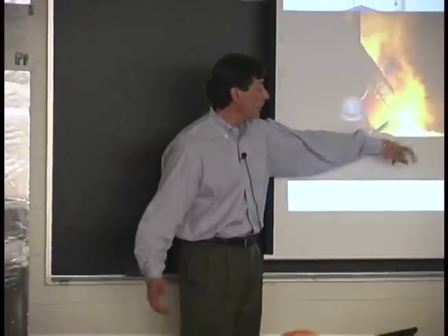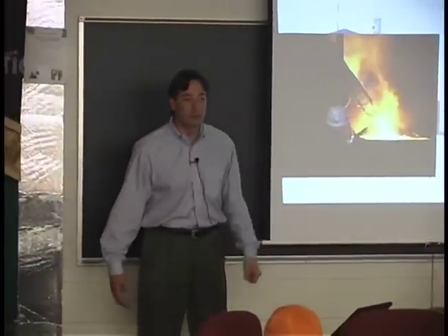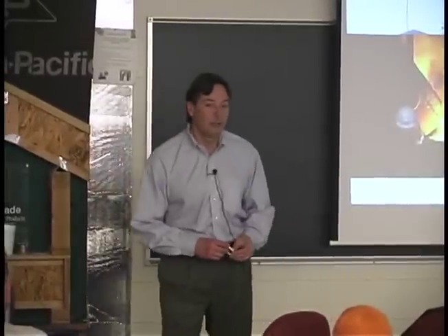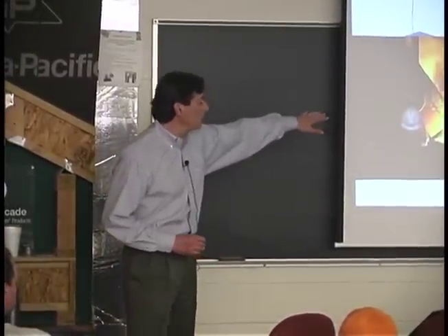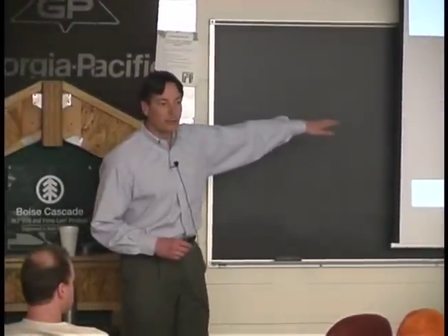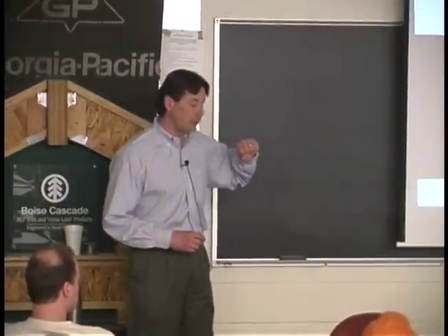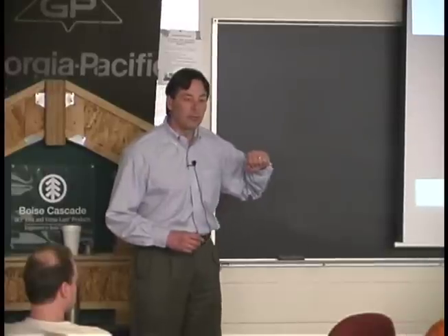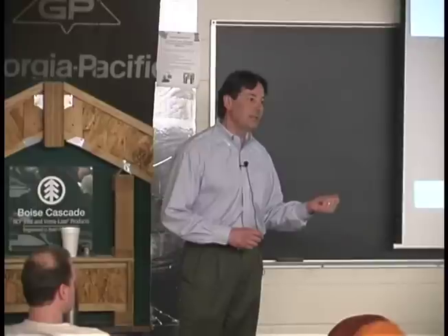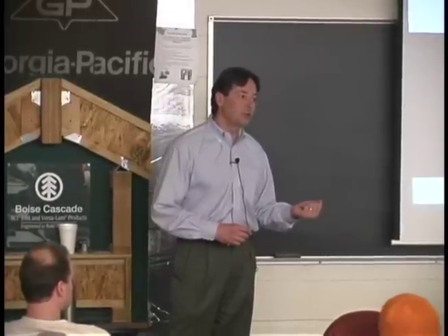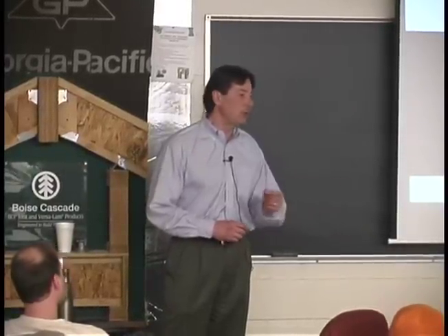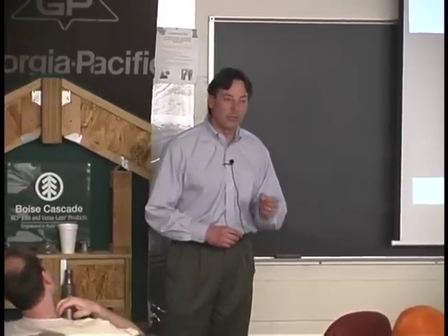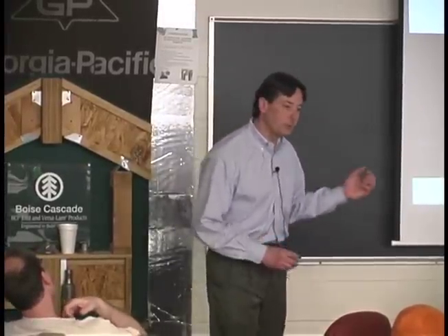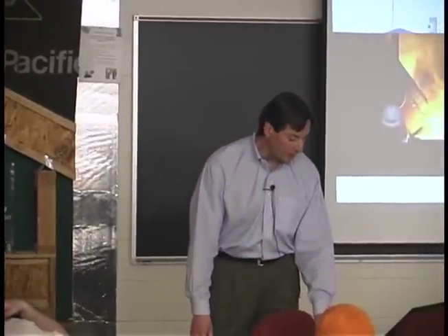This is actually the silicon metal coming off. This is the silica fume going up the stack. As it comes off the silicon, it's all gas, SiO gas. When it hits about 600C, it combines with another oxygen and forms an SiO2 solid. So you get this precipitation from a vapor to a solid, like the formation of a rain droplet. That is how the material ends up being so fine. Remember, we said it was 100 times finer than cement grains. It's captured smoke is what it comes down to.